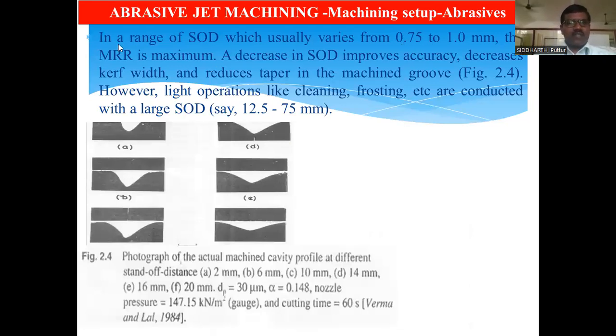The standoff distance usually varies between 0.75 mm and 1 mm. So the distance between the nozzle tip and the workpiece varies between 0.75 mm and 1 mm. In this condition, we get the maximum metal removal rate. A decrease in standoff distance improves accuracy, decreases the kerf width, and reduces the taper in the machined groove. That is shown in 2.4. However, light operations like cleaning, frosting, etc. are conducted with a large standoff distance, like 12.5 mm to 75 mm.